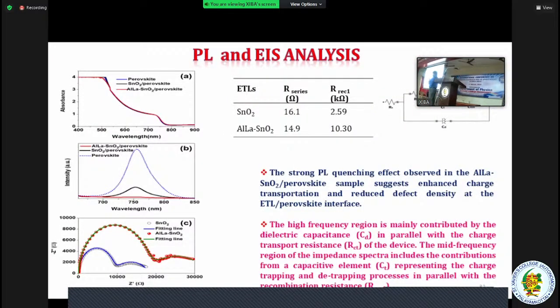So that one is the PL, photoluminescence measurement. Here you can see this intensity is getting reduced. There is a quenching of the light intensity. This is very, very important. Actually, the quenching is the most important. Why? Because when you reduce the intensity, that indicates how well your ETL layer is present. Suppose the ETL layer is defect free, then the quenching will be more, a much larger reduction in the intensity. So in our case, that is aluminum lanthanum tin oxide, we got almost zero intensity. That indicates your ETL layer is 100% covered.